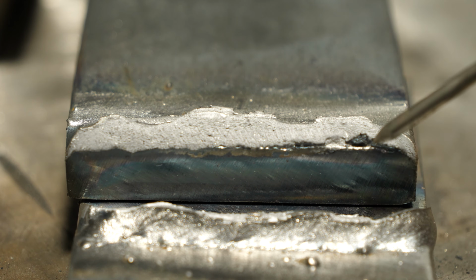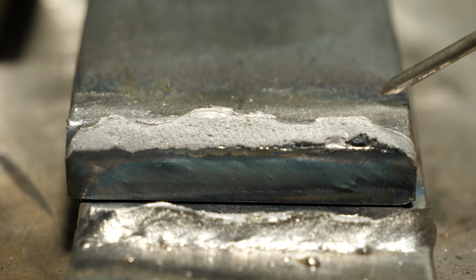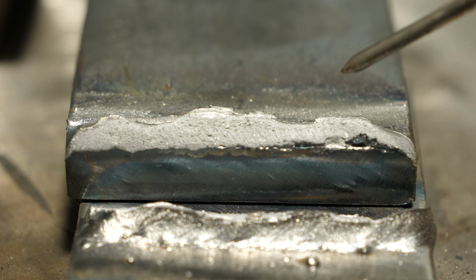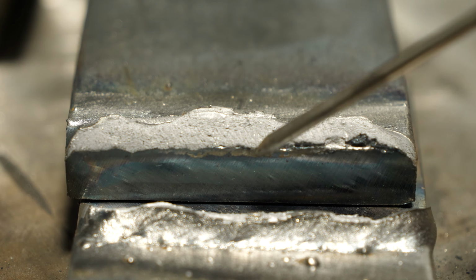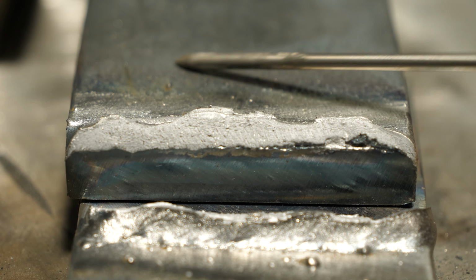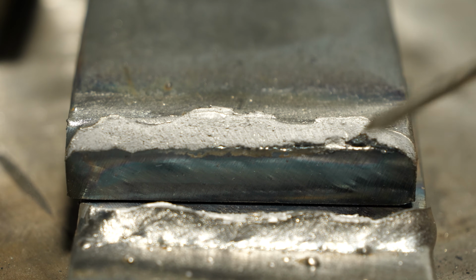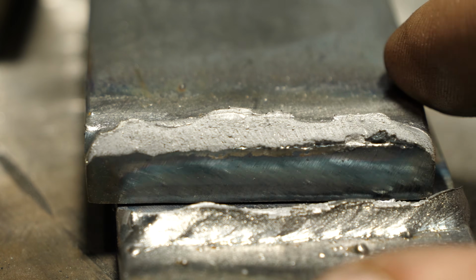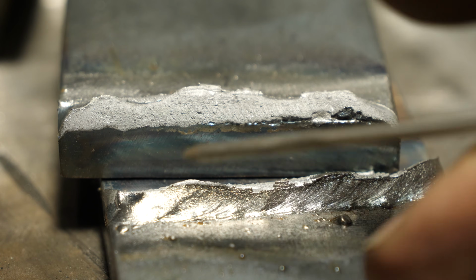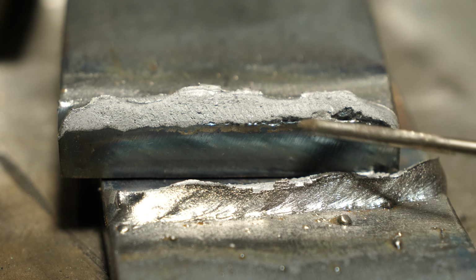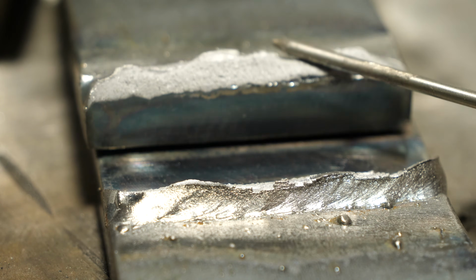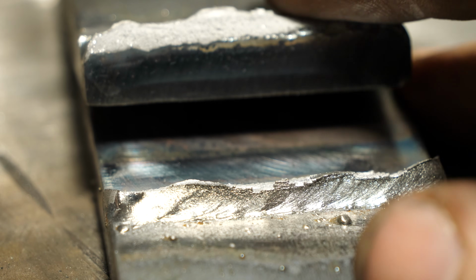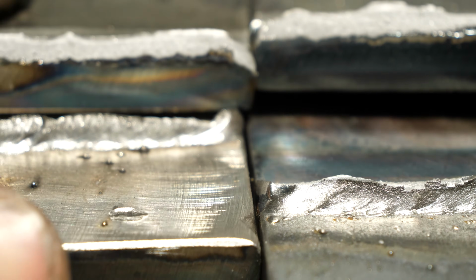With stick, you can turn up hot start a lot to where it boosts the amperage. That helps. With MIG, you can do run-in speed control. You can also just set your settings way hot, and especially on this plate, hotter settings would definitely benefit it. I mean, this is about 195 to 200 amps. Realistically, for 3/8 plate, you'd want a 240 amp MIG welder, and a lot of this would be improved with the additional heat. But for you home hobbyists with your home hobby machines, this is about the best you can expect out of it. And with the preheat, there is more fusion. There is no doubt that the rough area is only maybe a quarter, a third of it, and then everything else is broken down better when you look at it. And I'll put the worst and the best side by side so you guys can really see what I'm talking about.